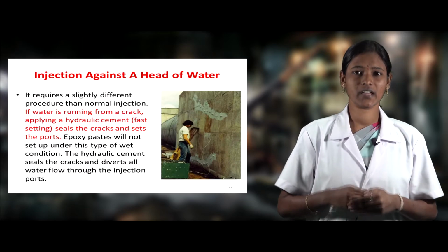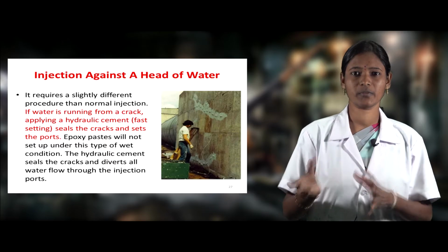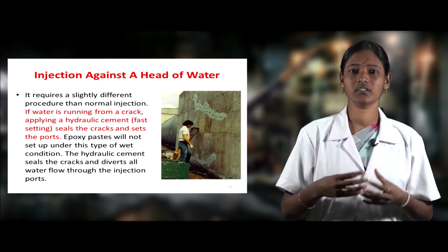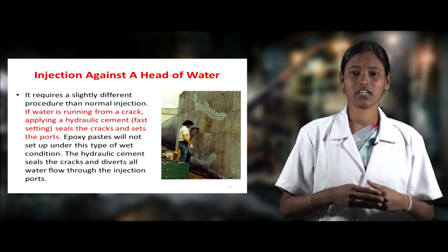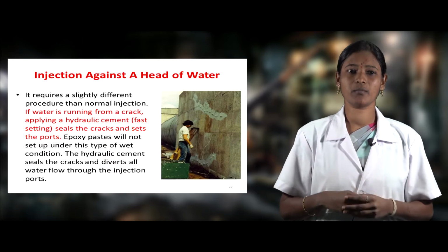Next is injection against a head of water. It requires a slightly different procedure from normal injection. If water is running from a crack, applying a fast-setting hydraulic cement seals the cracks and sets the ports. Epoxy paste will not set up under this type of wet condition.